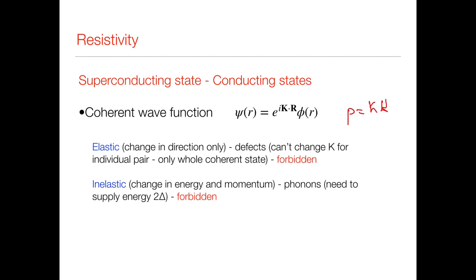Now we can have elastic collisions, so that's a change in momentum from a defect. A Cooper pair could come along and bump into a defect and try to change its momentum. Well, it can't, because all Cooper pairs have to have the same wave function. They have to have the same momentum. So if our Cooper pair had a different momentum, it wouldn't be part of the coherent ground state, and in fact it would therefore lose its energy. Okay, so we would need to have a change in energy, and that's not an elastic process.